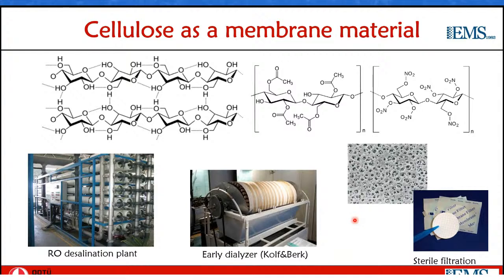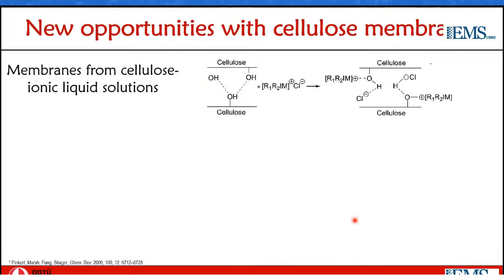Now, after more than half a century, with new developments in cellulose solvents and with cellulose-based nanomaterials such as cellulose nanocrystals or nanofibers, we want to reconsider cellulose as a membrane material. So within this context, I will talk about three different ways of fabricating cellulose membranes. The first is making cellulose membranes by using cellulose ionic liquid solutions with phase inversion, which is actually the most common membrane fabrication method, but could become more interesting and perhaps applicable with developments in ionic liquids as cellulose solvents.